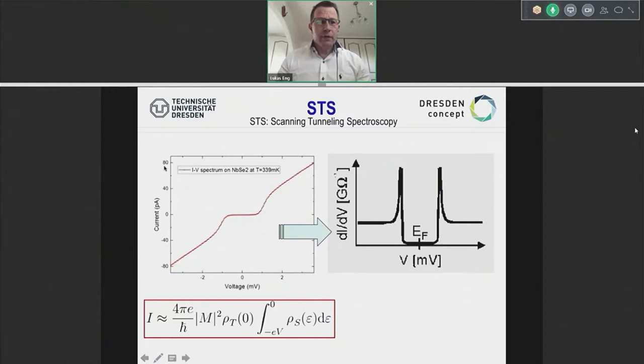And you can see this is quasi-ohmic, but has some kind of differences. And if you take a derivative of that, dI over dV, like shown here, you see that this cartoon transfers into something where we have really high densities, like shown here, at certain voltages, a band gap, and another density. And if I turn this cartoon to the right, as you see now, the axis upright is the energy axis, and you see exactly, like you learn in class, the energy levels of this system. So it's really easy how this goes.